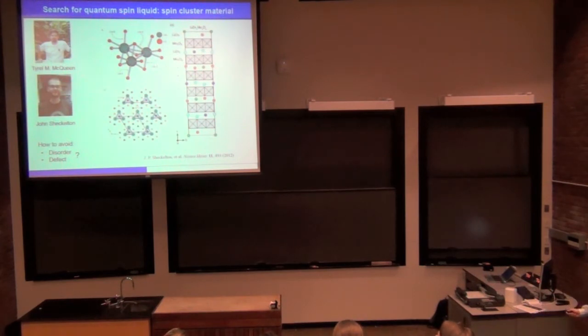So in the study of quantum spin liquids, usually there are a couple of obstacles. From a material point of view, one obstacle comes from the disorder and defects of those materials. When you have even a small amount of disorder, the perfect balance that comes from the geometrical frustration is disrupted. As a result, at low temperature, instead of having a quantum spin liquid, the material can go into a spin glass state, or it can freeze, or sometimes it can have a conventional long-range order state if you have disorder or defects.